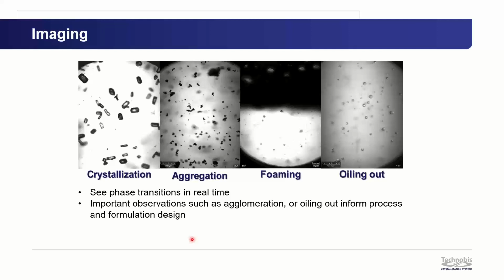And some of these factors you can't see with Raman, so such things as oiling out or agglomeration need to be seen by camera imaging. And that's a similar problem of being only really usable at 100 milliliter scale. But with the Crystalline, we can get down to 2.5 milliliters. And we can see the crystals.